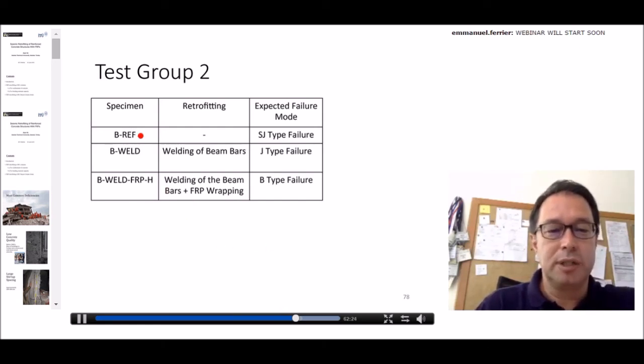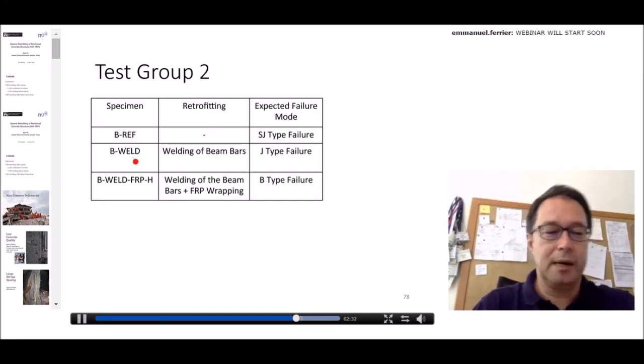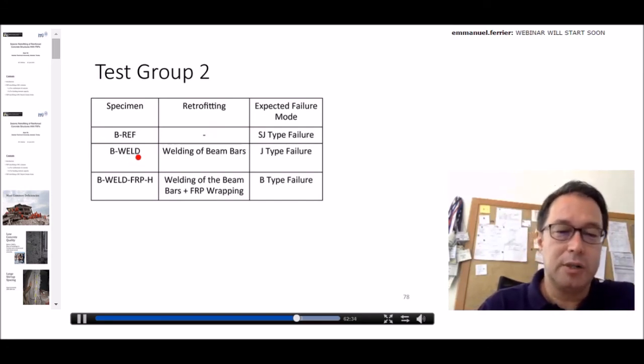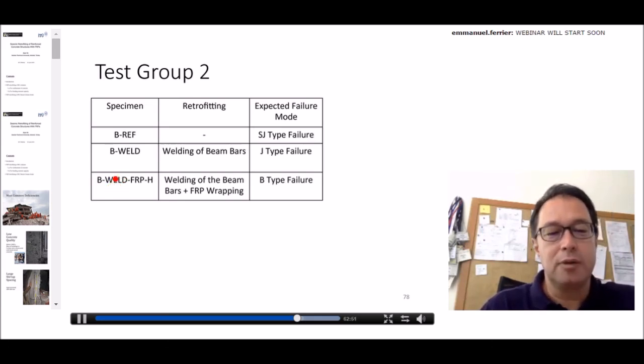One is the reference specimen, the control specimen. One is the specimen which corresponds to the previous joint tests, where we only weld the hooks of top bars and bottom bars to each other, with no FRP retrofit. And finally, another 3-dimensional specimen which corresponds to the joint that I have shown you before, where we also weld to avoid slip, and also apply FRP on the beam column joint to avoid beam shear failure. And the conclusion is given here as a summary.